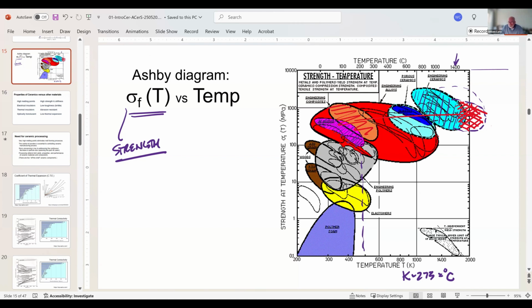But you can see then the strength at temperature. As our temperature goes up, in general, strengths go down. We are pretty seriously limiting our materials based on a temperature limitation. So polymers and elastomers have low temperature maximums and relatively low strengths, 2 orders of magnitude below what you would see for ceramics. Our engineered polymers get better, and our composites then improve things above that. So here's our engineered composites, right? What we have is we are tailoring the materials for the application temperature.